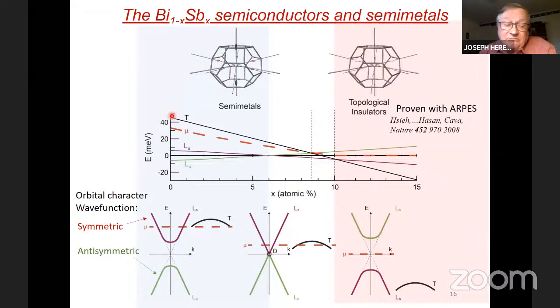Now the T hole band, which is the trigonal pocket, comes down in energy. Unfortunately, at the point where the material has a Dirac point, there are still T holes. So this is not a perfect Dirac semi-metal. It's still a quite conventional semi-metal with holes at T points and electrons at L points, although the L points have a Dirac dispersion.